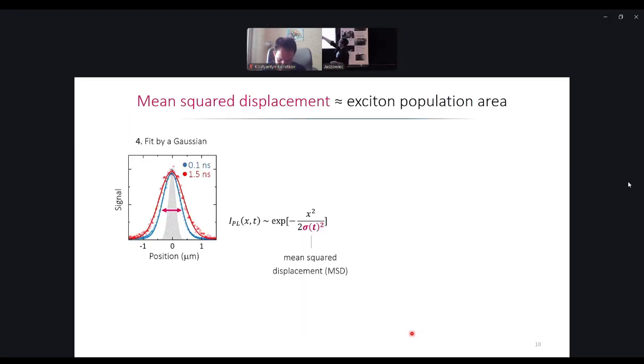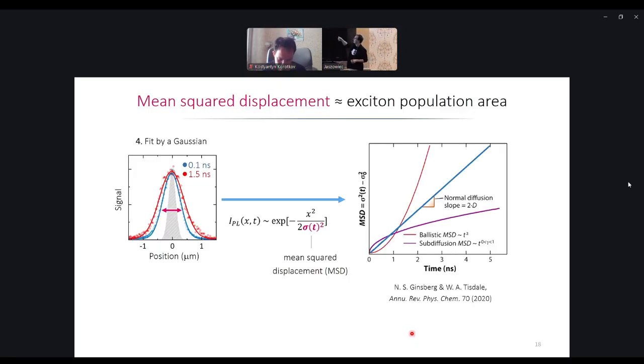Regarding the analysis of the data, so let's say we acquired the signal, be it in pump probe, be it PL, then, for example, this would be the extracted quantity. It's called mean square displacement, MSD, but in principle it's a variance of the Gaussian that you use to fit. And then you have characteristic regimes. If your area, so this is the square of this, yeah, you see the square, the area increases linearly. In most cases, this means you have free diffusion. There's a few exceptions, but we'll not discuss it here. If you have a question, we can talk later. But if the area grows linearly, then you are in the regime of free diffusion.